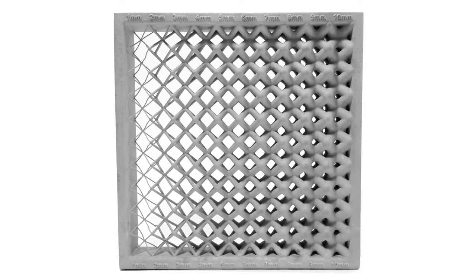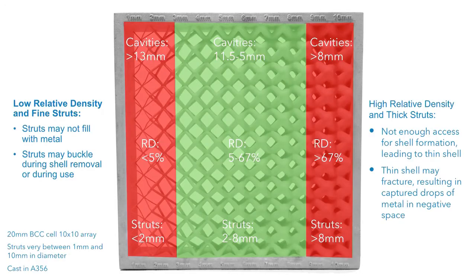So we did a couple of these test pieces to come up with some basic design rules. We generally found once you have cavities above 13 millimeters, you have plenty of access. But we were doing a body-centered cubic lattice cell here, 20 millimeter unit cell. Once we had struts below 2 millimeters, we started seeing those struts breaking during the pattern portion of the process. And likewise, when we went to higher relative densities, so on the far right there, struts of greater than 8 millimeters, we started getting below that twice the shell thickness criteria, so less than 8 millimeters cavity size. We started getting incomplete shell buildup there and getting defects.